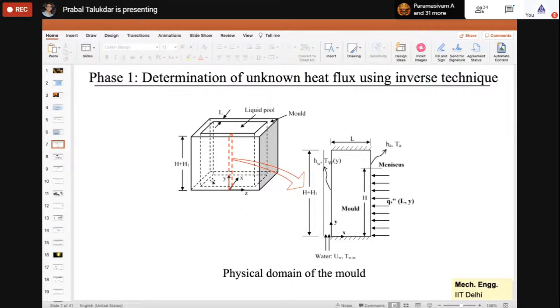So this is the first part of the problem, where we have used the inverse technique to find out the heat flux. So you take any mold, like this, again you can see the mold here, a rectangular mold, and liquid metal is coming from the top and going out, right? So you take any section of the mold, and this is the section of the mold which is shown here. And from the industry, actually, they use certain sensors, and from those sensors they get certain temperature data in the mold. Now in this problem, we know some temperature data, and the boundary condition, the heat flux inside, is not known to us, right? Because that is what we are going to predict in this problem. So the boundary heat flux at the inside is not known to us. This is unknown to us.